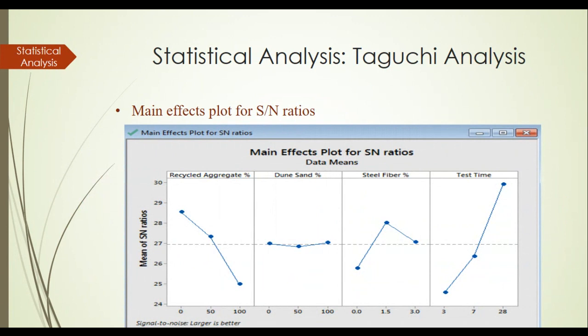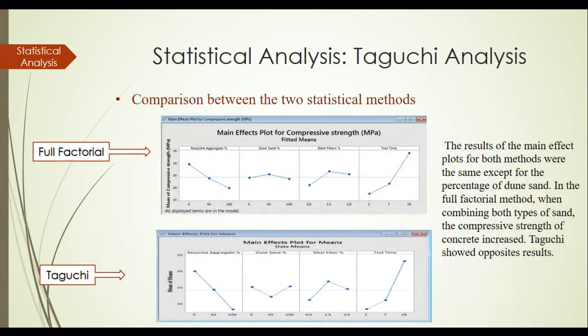Similarly, for the sensitivity, the signal to noise ratio here follows almost the same as the effect on mean. So if we would like to conduct a comparison between full factorial results, recommendations, and Taguchi results, basically, as we can see here for the recycled aggregates, almost the same recommendation, almost the same behavior. For the dune sand, except here the 50% of dune sand, the other results are very comparable. And the steel fiber percentage is exactly the same recommendation, same as for the curing time.